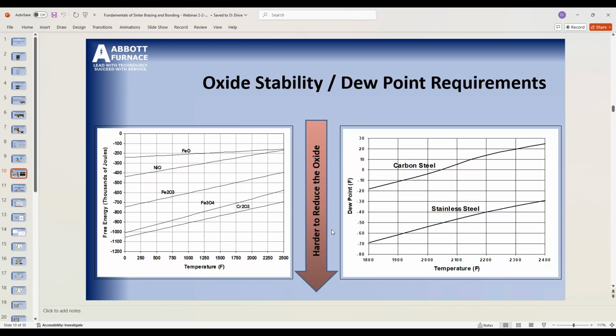And so often in our furnaces, or in our processes, we talk about dew point. And the dew point you need depends on the chemistry of the metals, right? And I don't want to get into the weeds of free energy and all of that, but the gist of this is, if I look at these lines that represent the energy associated with the oxides, okay, what you find is the lower on this graph you are, the more stable the oxide is. So the more the metal wants the oxygen. So that means we have to have a lower dew point to reduce chromium oxide than we do to reduce iron oxide. So on the right-hand side here, you can see regular carbon steel is actually easier to clean up than, say, a stainless steel that contains the chromium.